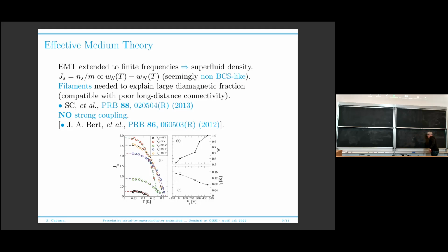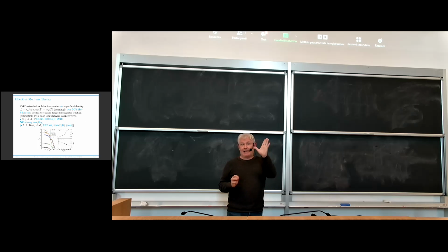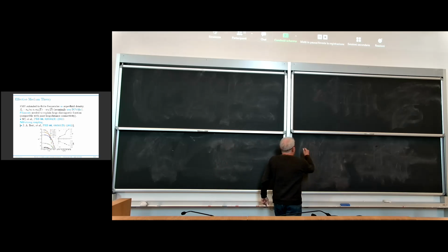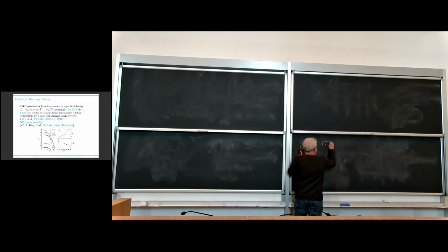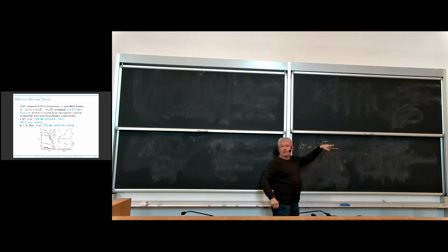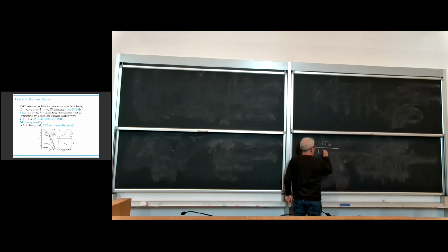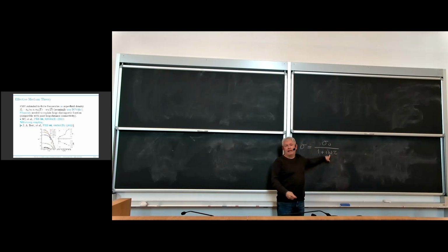I see it. So I will make a very, very stupid model, which is the Drude model. But this, in my opinion, gives a very nice example of what goes on if you are discussing the superfluid response. In the Drude model, the conductivity is sigma naught, a constant, I will write this constant in a while, divided by 1 plus i omega tau, where tau is the scattering time and omega is the frequency. This is the conductivity at some finite frequency, real and imaginary part.